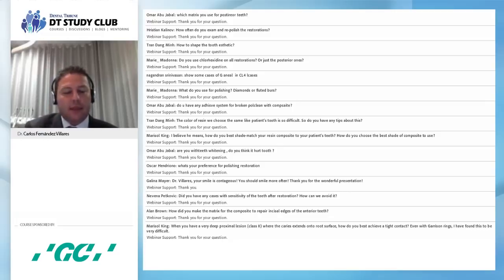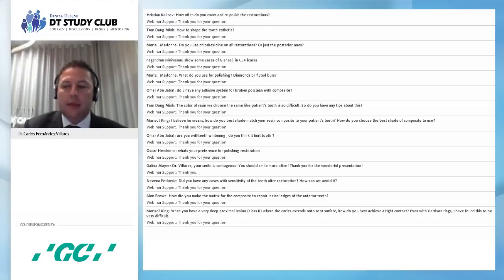Sometimes the problem is that if we try to manage the restoration subgingivally, it's very difficult to have a very good contact point that allows us to make a good function. So if you don't want to make an indirect restoration, in that situation we make it in 2 steps. First, we make the margin elevation, and then we change everything and put a sectional matrix system to make the contact area. But I will always do it in 2 steps. The best way is to make the second step in an indirect way with an onlay or an inlay.